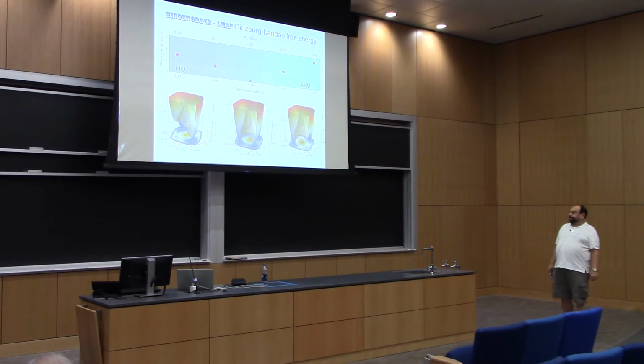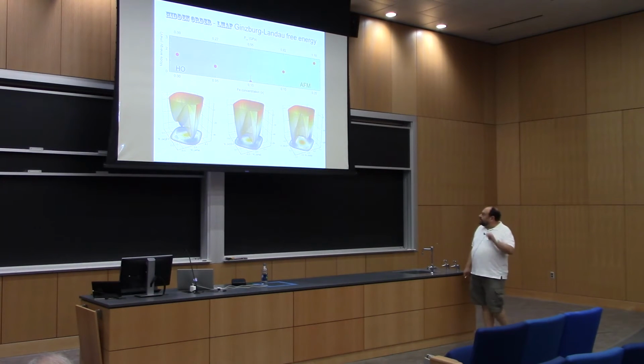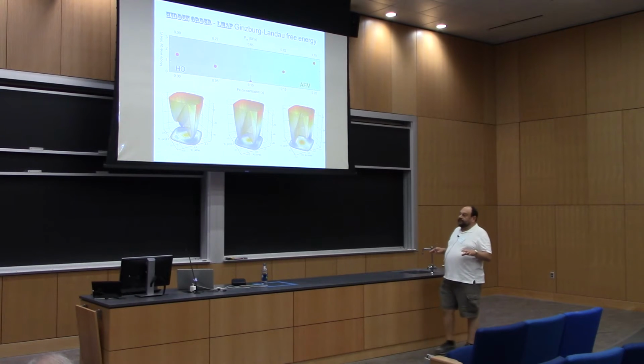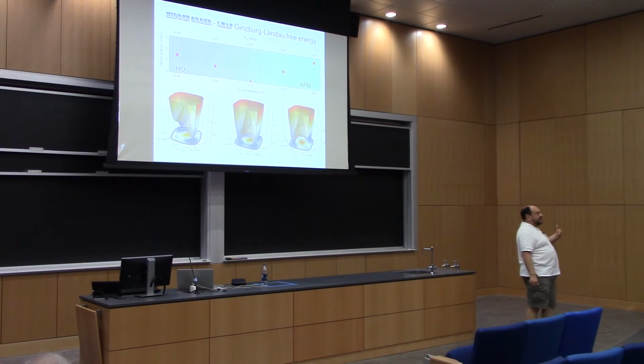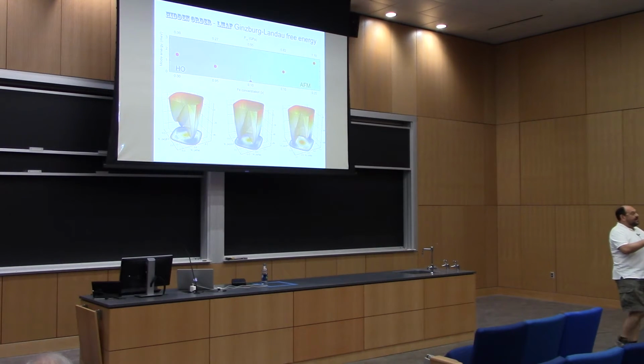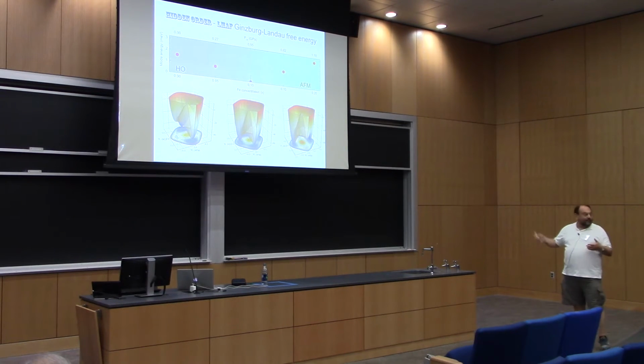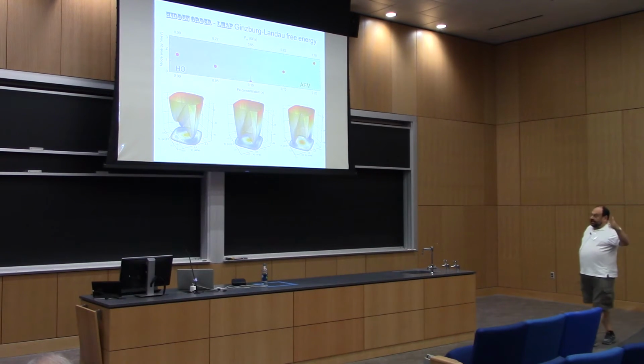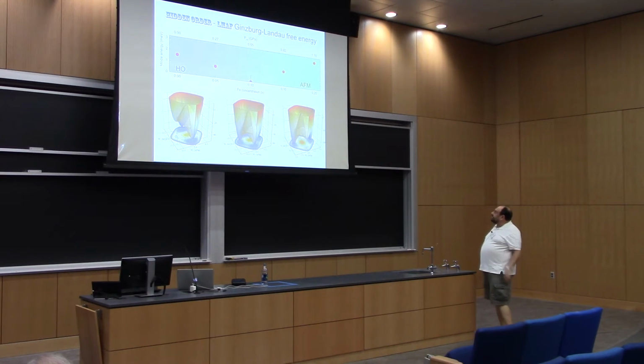So how to explain that? If you go beyond the very naive picture, where we say that this excitation is just a naive, local excitation between the local crystal field levels, on the left case it would be a transition between A2G and A1G. Then in that local picture, when I apply pressure, the splitting gets reduced, the levels cross, and my A1G becomes the ground state. So no broken symmetry is required to go into the magnetic state, except that the mixing will reduce the moment, but there is no broken symmetry in terms of space group.